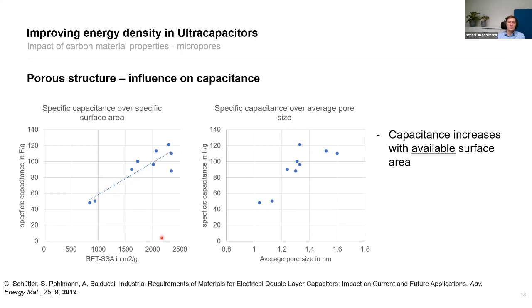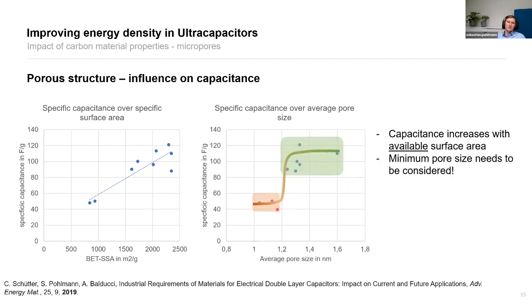And what we did then is we checked the influence of the pore size. How can you impact that capacitance by changing the pore size? We found that for different pore sizes, you also get a sorting by capacitance. If you have pores that are way too small, you don't get enough capacitance because the ion just doesn't fit in all the pores anymore. The average pore size is too small for the ion, whereas, because these were all done with the same electrolyte, when you get to a larger pore size, you can get the ions in and utilize the surface area.